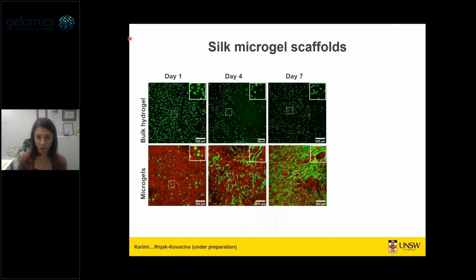And when we take these and we put cells in them, if you encapsulate cells in vitro in these, you can see live cells staying green. And in our bulk hydrogels, they're happy enough. They stay alive for 7 days, no issues, but they're not exactly spreading and they're not proliferating much. Whereas if we encapsulate them between our microgels, those cells start off rounded and then they start spreading and proliferating and really modifying their environment.